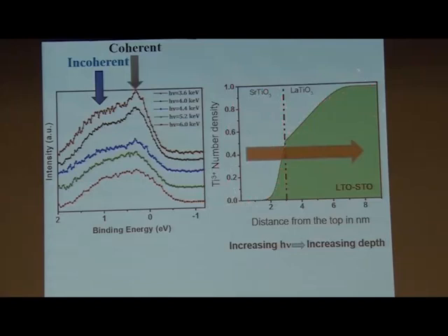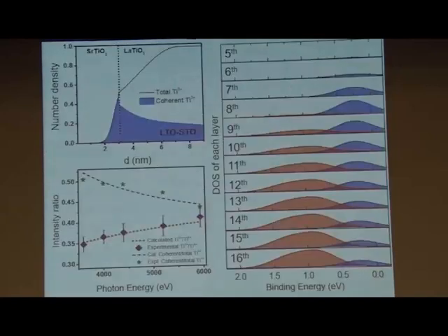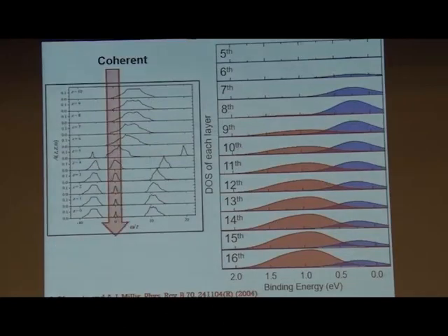This is almost 1 electron when you go deep down in. Near the interface, strontium titanate gets about a nanometer or so thick 2D electron gas, and it leaks into inside. It borrows the electrons from there and goes into that side, also on the STO side. And the spectral features, if I extract, let me point out here, yes. So it compares exceedingly well with this theoretical calculation, and that's why I've shown you.